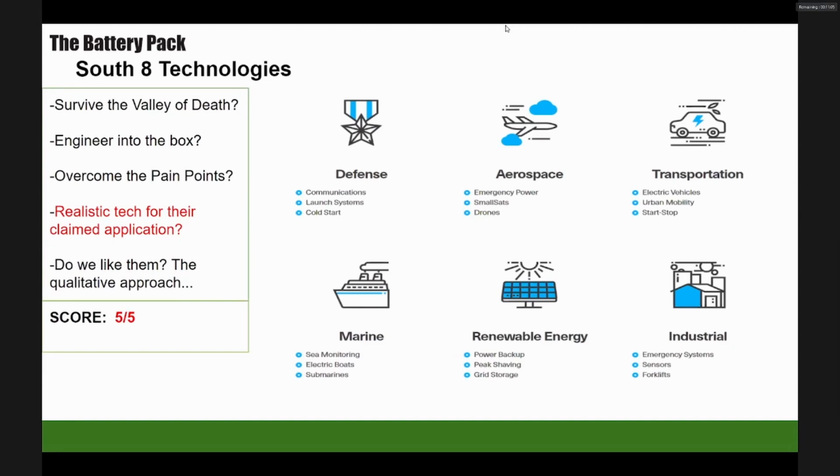The safety aspect, I would argue, is extremely high, because the safety on this is going to become an issue where, when does it vent? So let's just say we have a thermal situation where stuff around it's getting really hot, you're heating the gas inside, it keeps getting hotter, or maybe you're running into an overcharge where the gas is getting extremely hot. The CID will break, all the liquefied gas will become gas phase and then just leave the cell.